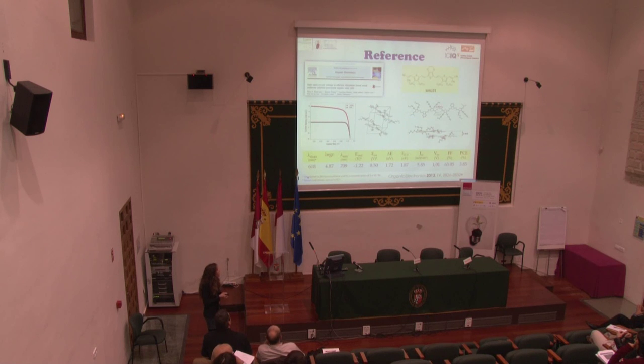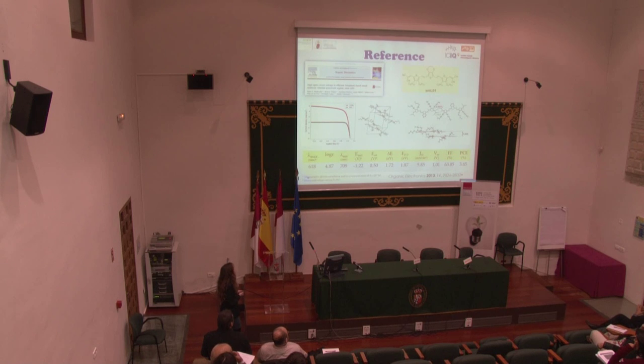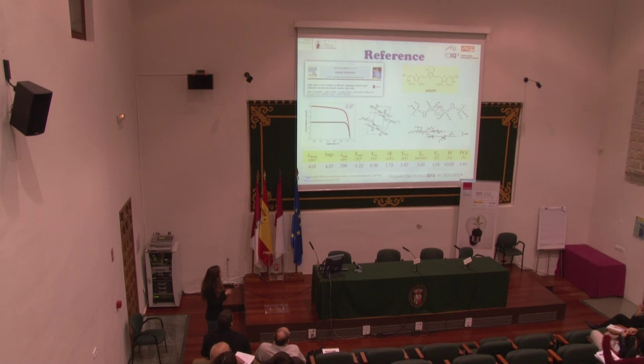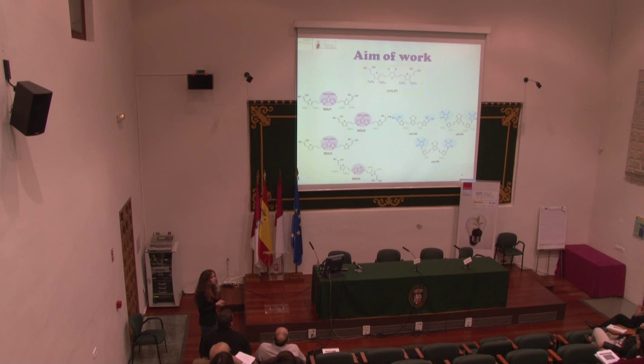Last year, we reported this small molecule for solution-processed organic solar cells, achieving a PCE of around 3.85% and a good open-circuit voltage of 1.01 volts. We also studied the molecule by X-ray diffraction and observed that the molecule forms extended linear networks through hydrogen bonding between the NH proton and a cyano group of an adjacent molecule. These networks stack through each other at a distance of 3.5 Å.